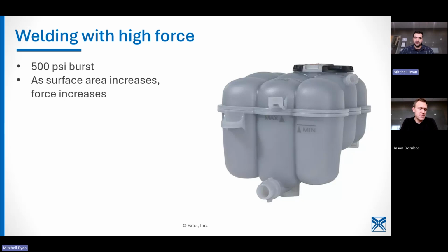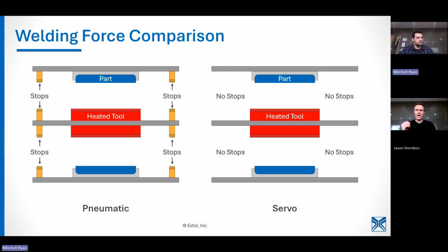I can say this too: there are a lot of applications where the weld rib width is designed to be slightly larger than the wall thickness of the part, maybe 20%, maybe 50%. By doing that, you're able to maximize the strength of the weld so much that the weld is not what fails when you run strength tests, whether it's a tensile test or a burst test. It's failing elsewhere because the weld becomes stronger than the wall thickness.